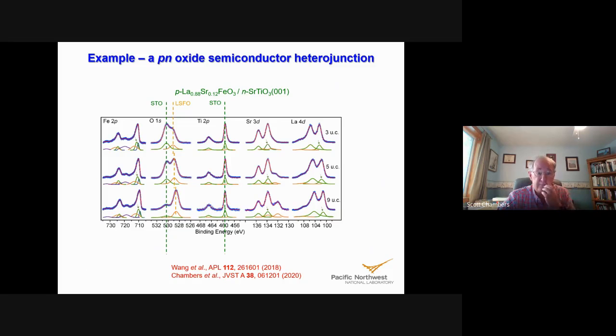Some of the titanium from the substrate goes out and occupies iron sites in the film. And so you have, in addition to the substrate feature, which is the larger one, a second feature, which is titanium out in the LSFO. In the case of the strontium, you have strontium in both materials. So you have one strontium 3d 5/2 in the STO at one binding energy, and you have a different strontium 3d binding energy for strontium out in the film.